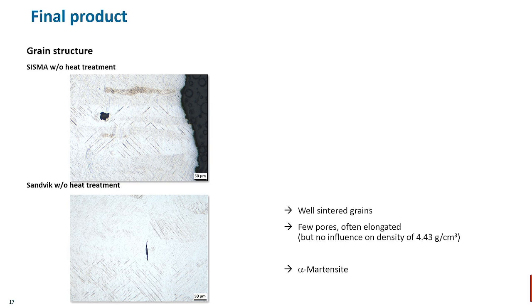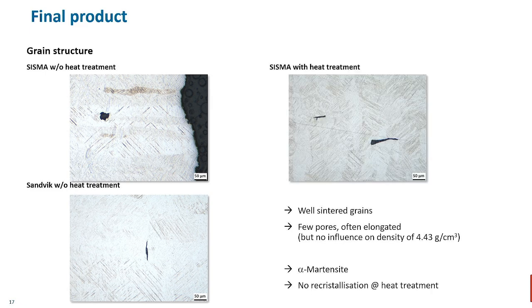We can look at grain structures, which are quite different from forged alloys. So we have here alpha martensitic grains, which is quite different from the bulk you expect from a nice titanium, aluminum, vanadium alloy. And yeah, pores within the samples.